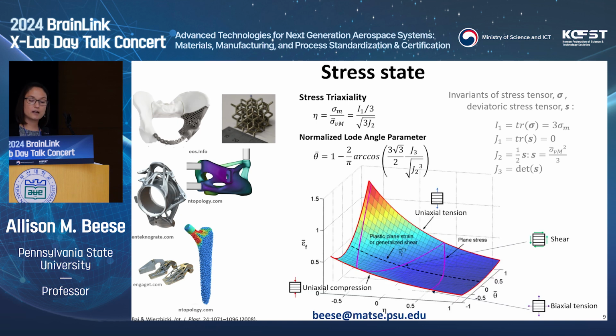Okay, so the reason that I bring these up is that for ductile metals, the amount of ductility that we have, so the vertical axis in this plot, is a function of those two parameters. So for any combination of these two, we can have a very low ductility over here, or we have a higher ductility over here. So the distance between your bottom plane and this surface, this fracture locus, tells you the amount of ductility in that stress state.